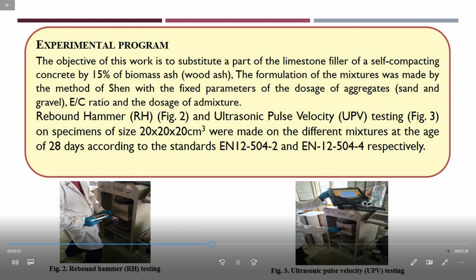The experimental procedure is to substitute limestone filler by wood ash in a quantity of 15%. We use the same formulation with fixed parameters of dosage of aggregate and ratio of water by cement. Rebound hammer and ultrasonic velocity tests were used according to the standard method.